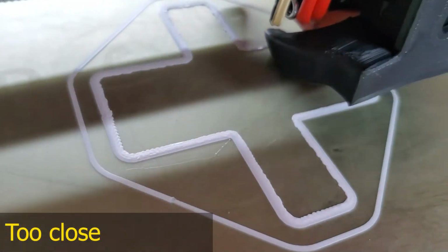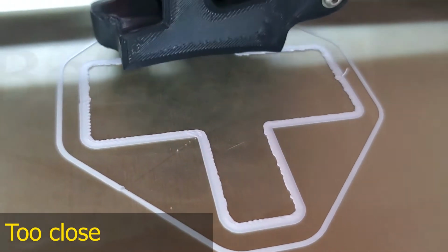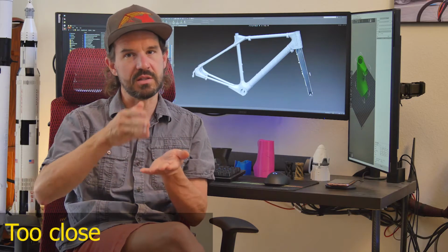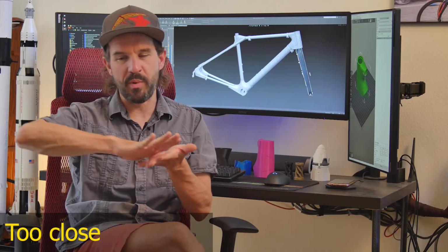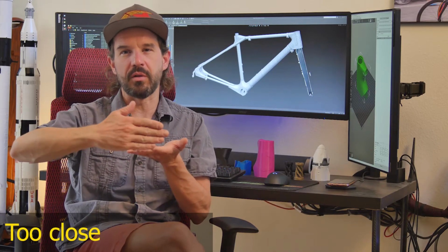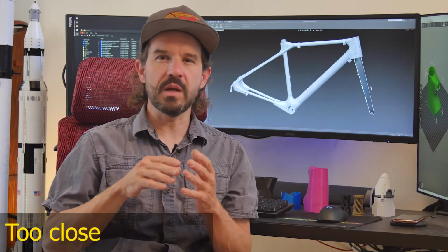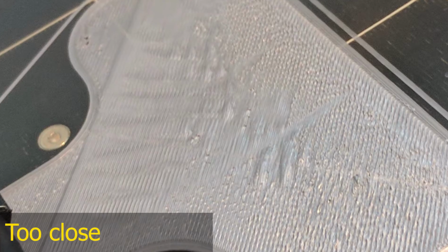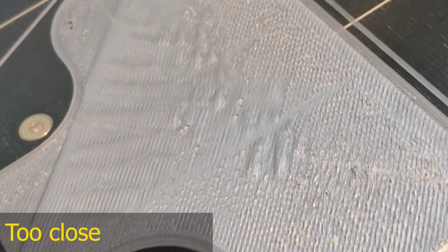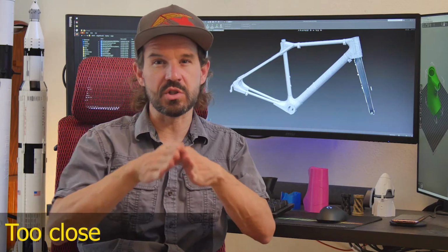You'll notice the material along the edges will start to get rough and jaggedy, and that's because again there's nowhere for the plastic to flow but out, so it just builds up along the edge. It will also cause a particular sort of striped, tiger stripe type pattern in a large flat first layer, because again, there's nowhere for the filament to go, so it just warps up.